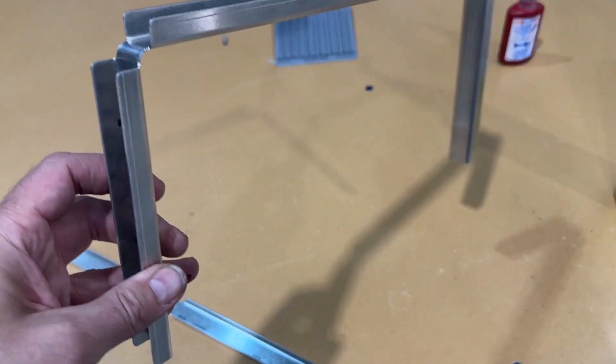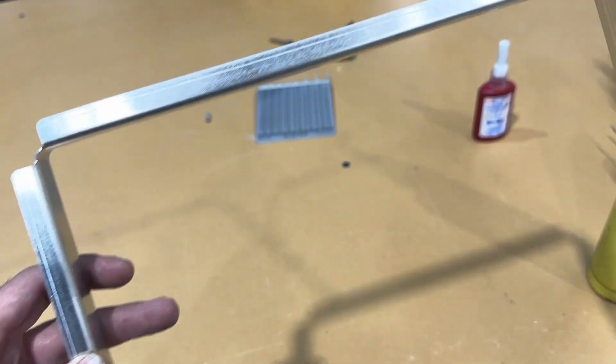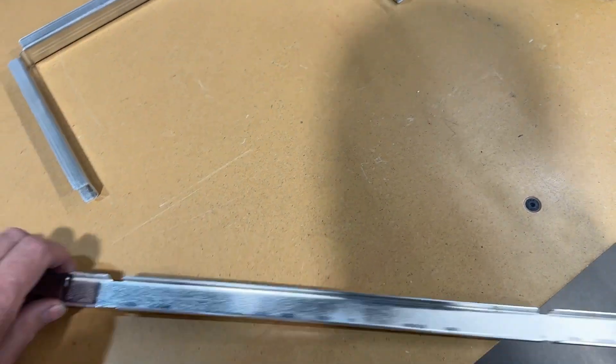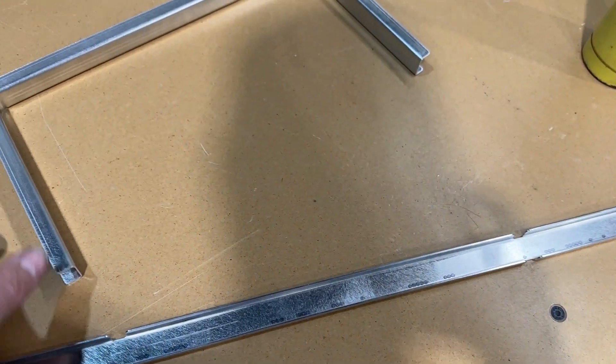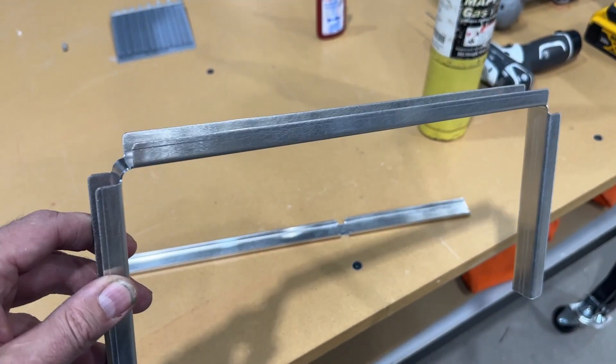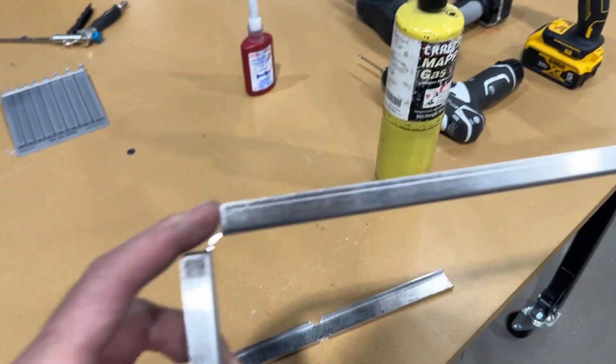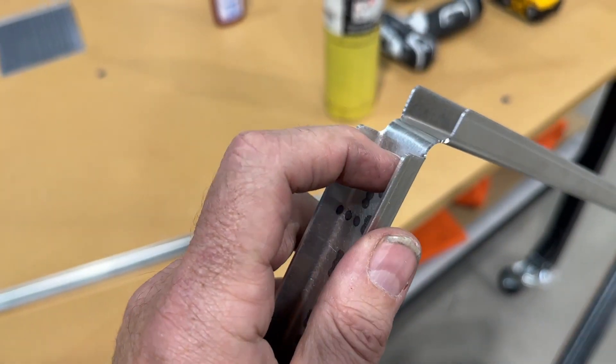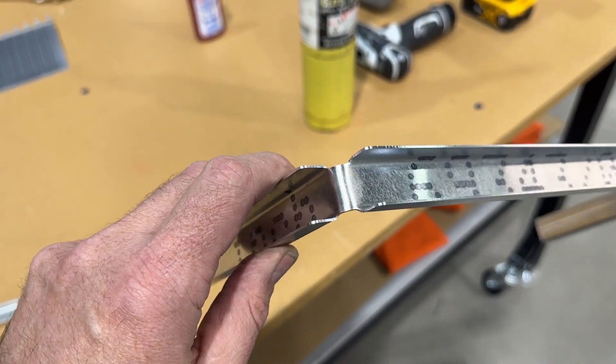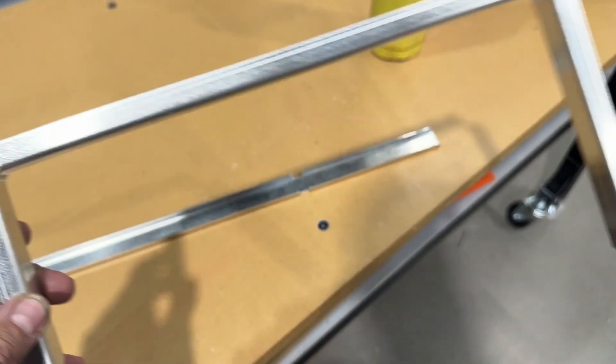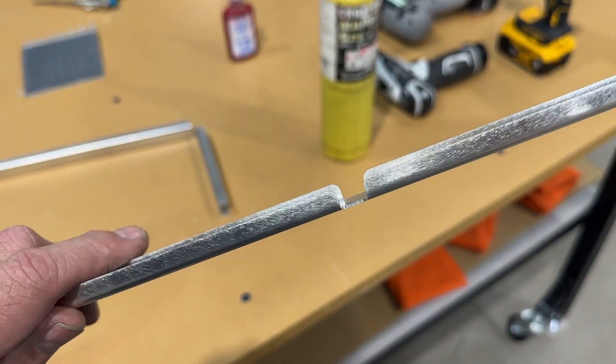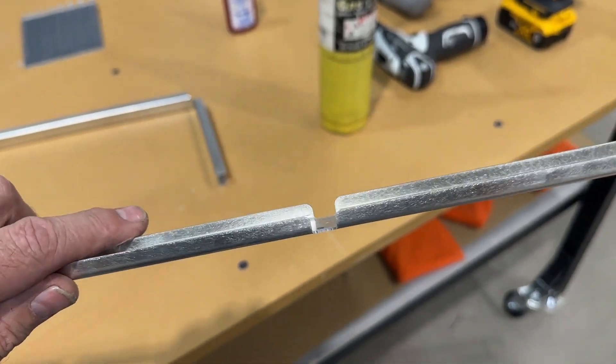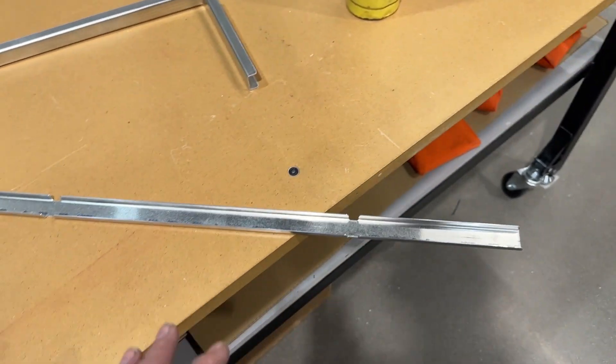Got one of my tank mount straps bent up here. One thing I do on a piece like this—so what they do is they notch it out there and got it ready for you to bend—what I like to do on a piece like this that isn't really a structural load-bearing piece, on a bend like that, I like to hit it with my torch and just anneal it about a half inch back on either side of the bend. Not a lot—you're just heating it up to the point where you're just annealing the metal just a little bit. And that's just going to reduce any stresses in the metal so that when you bend it, you should get a nice clean bend and a little bit less risk of cracking. Now it does weaken the metal; it does soften it in that area where you've annealed it. That's why you wouldn't want to do this on a high-stress component. But on a piece like this, no problem.